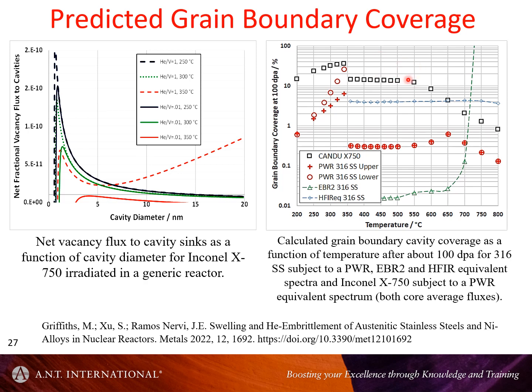But if we calculated the swelling, assuming a bias-driven growth of cavities, which is not the case, in fact, for our reactors, which are down at this temperature range, with increasing temperature, we'd actually see a decreasing coverage. And the cutoff is around about 350 to 400, so we arbitrarily put that in there, and that's when we get into the bias-driven growth regime. It comes in somewhere between 300 and 400 degrees C, depending on what one has for the cavity density, the dislocation density, the microstructure in general.